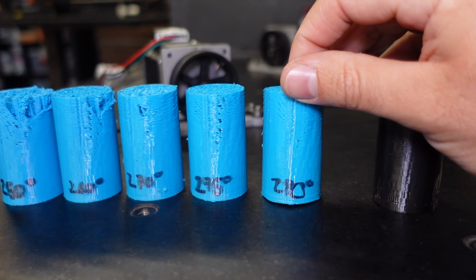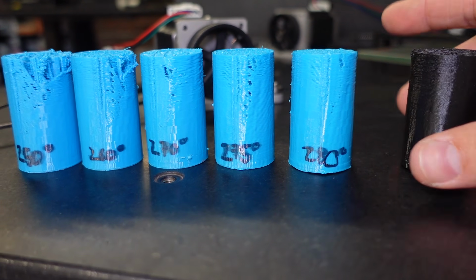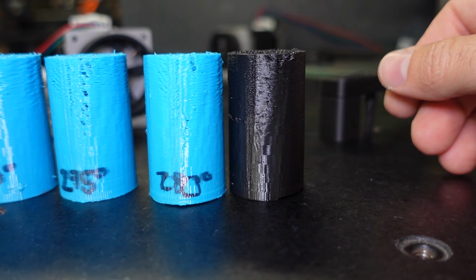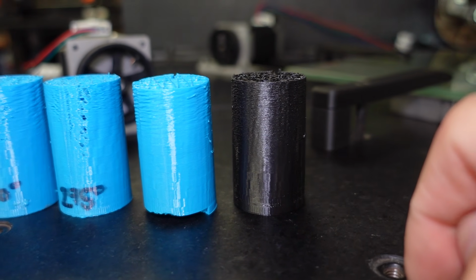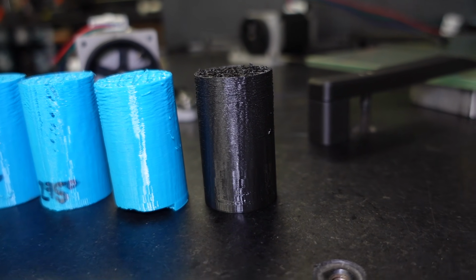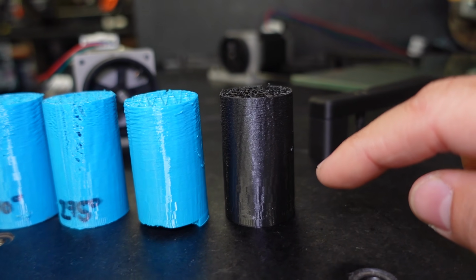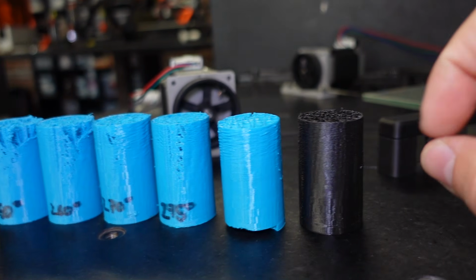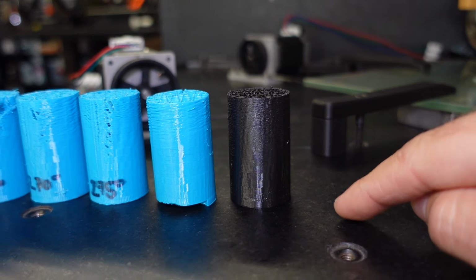This is the standard PET-G. This was at 280, and these seem to be about comparable in terms of extrusion quality, but this is 40 degrees lower, and this is kind of what I was hoping to see here. No problems at all reaching 1500 millimeters a second at only half a bar of cooling pressure. So same as here, I'm gonna go up and down a bit, see where we find our sweet spot, and I'm gonna show you the result.